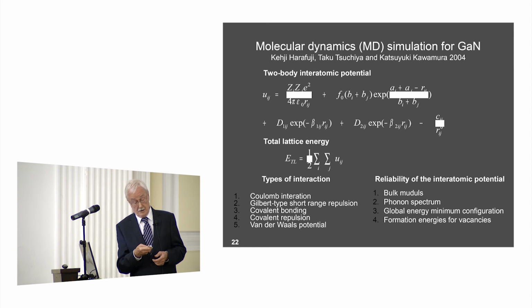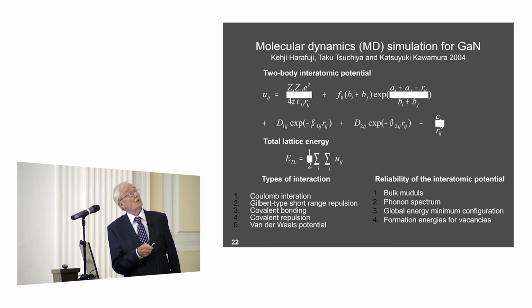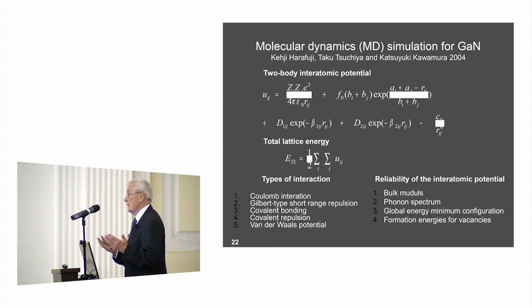But the theory of Harafuji, the molecular dynamics simulation for gallium nitride, includes this possibility. And what is shown here is the interatomic potential which he uses in his calculations, which looks very discouraging. You have five parts of this potential. They are listed here: Coulomb interaction, Gilbert type short-range repulsion, covalent bonding, covalent repulsion, and van der Waals potential, and many constants. So it's really very discouraging.